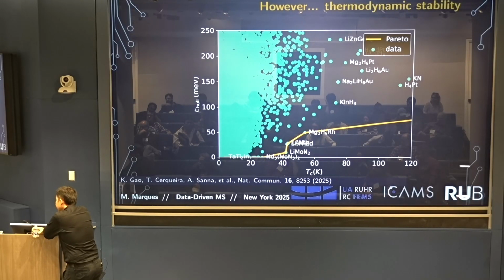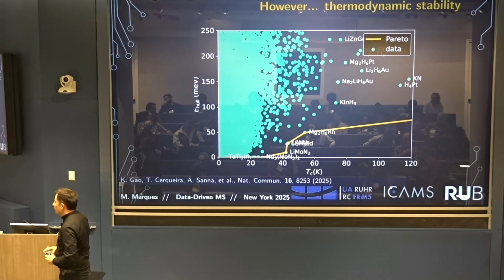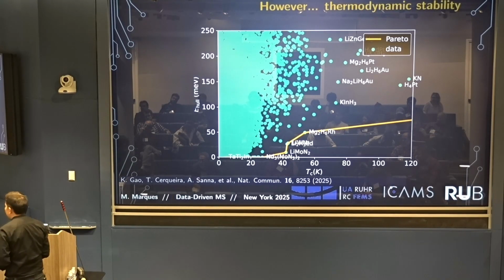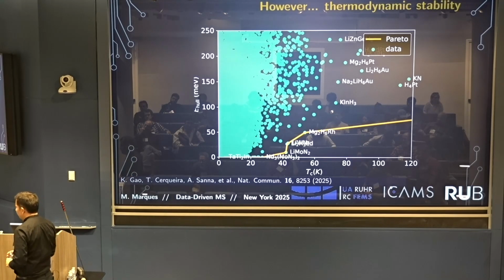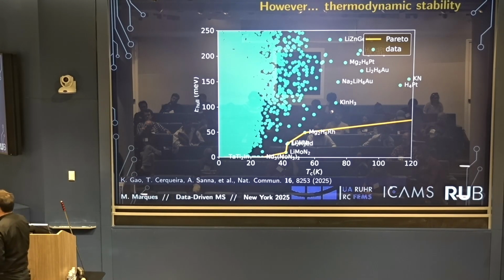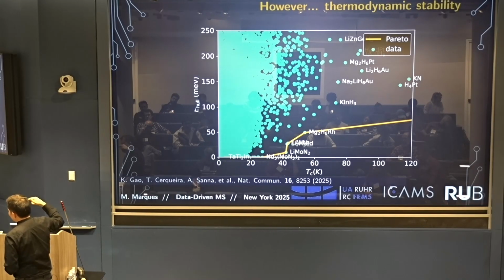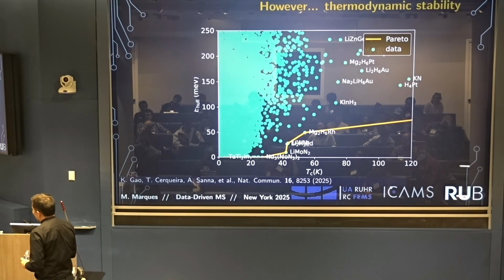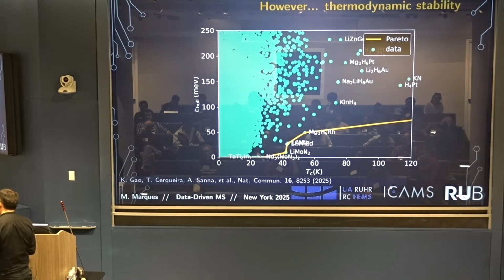Yeah. Do you see any sign of that in the areas that you're concerned with, where you're adding things to databases? Here there is not a very big problem because it's DFT data. So the database is relatively clean in that sense. Now, there is a bias that comes because the compounds chosen to go into the database are generated by machines again. And that's not quantifiable. It's very hard to know. So what we do is periodically retrain the machine, starting from random weights, hoping that the systematic errors are different.